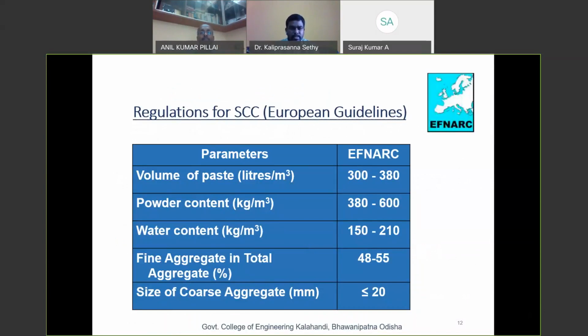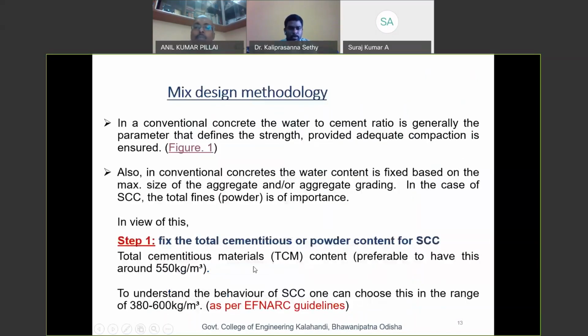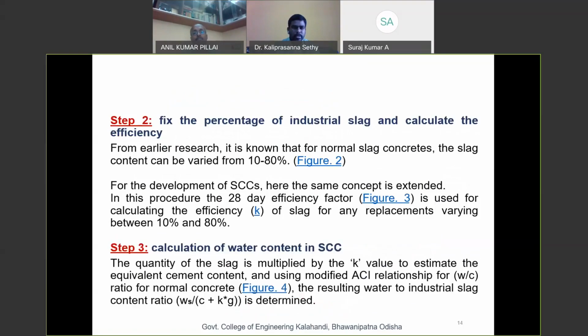From the EFNARC guidelines, as per the parameters, we have to set the powder content in between this range, 380 to 600. Based on this, we have set our powder content as 550 kg per meter cube. You can understand why we have chosen these parameters from the EFNARC guidelines, which I already showed you. In the next step, once we fixed our powder content, we fixed the percentage of industrial slag and calculated the efficiency also.